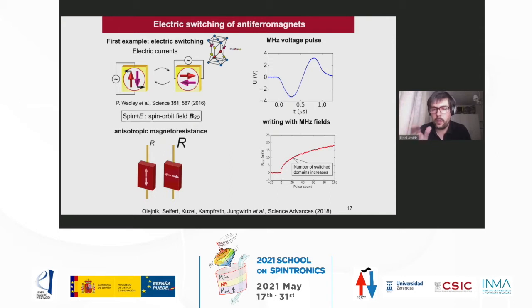This is like 10 to the 6, a million times larger than a picosecond. What they observe is that after applying one pulse, the magnetoresistance increases, and if they apply more pulses, the magnetoresistance increases even more, and this is a signature that the number of switched domains has increased.